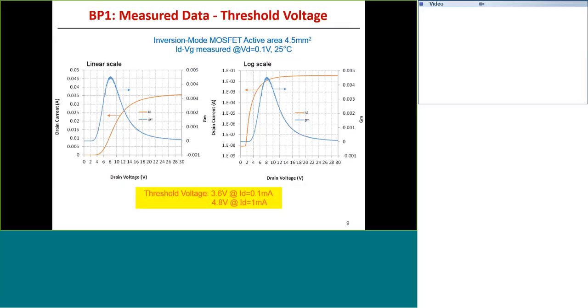So let me show you the results on our inversion mode MOSFET. These have an active area of 4.5 millimeters squared. And here we are showing you data on threshold voltage measured at two conditions. And these are very reasonable threshold voltages of 3.6 volts, for example. So the left-hand side chart on this shows the linear scale for the drain current, and the right-hand side shows the log scale. And so these are very good transfer characteristics.